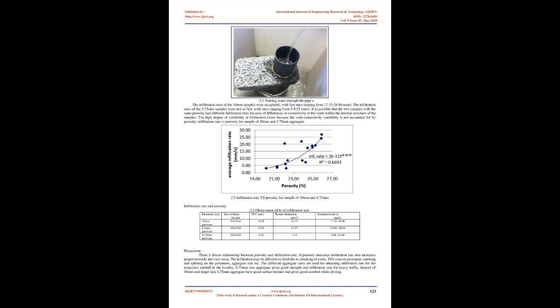The infiltration rates of the 10 mm samples were acceptable, with fast rates ranging from 17.37 to 26.86 mm/s. The infiltration rates of the 4.75 mm samples were not so fast, with rates ranging from 3 to 8.55 mm/s. It is possible that the 2 samples with the same porosity had different infiltration rates because of differences in connectivity of the voids within the internal structure of the samples. The high degree of variability in infiltration exists because the void connectivity variability is not accounted for by porosity. Infiltration rate vs porosity for samples of 10 mm and 4.75 mm aggregate. 2.5 Infiltration rate vs porosity. 2.2 Observation table of infiltration test.